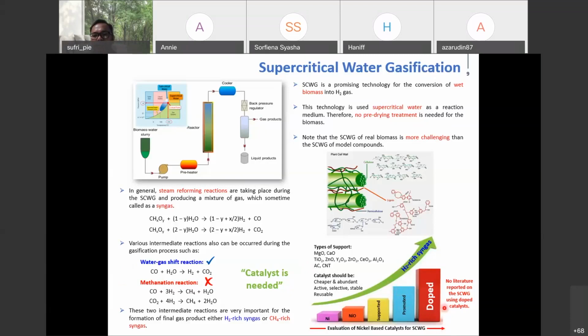In this study, this is my novelty, the novelty of my research. I tried to introduce another catalyst structure. Instead of using a support type of catalyst, I introduced the doped catalyst structure. From my survey during that time, no literature reported on supercritical water gasification using doped catalyst. But don't get me wrong, of course, doped compounds like alloys are widely studied by other researchers, but not for this application, for other applications.